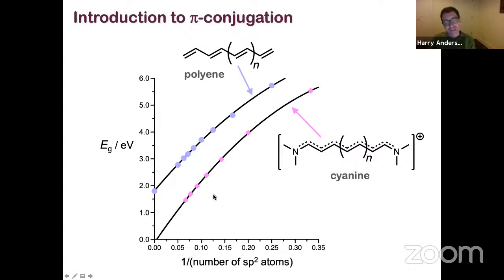But I think you'll see that there's something a bit paradoxical here, because if it was an infinitely long chain, then the end groups wouldn't make any difference. And then it would be essentially the same as the polyene. So the two things must converge where they're infinitely long. And so what must happen is that actually, for a certain length, this does undergo a Peierls distortion and must rejoin the curve for the polyene.